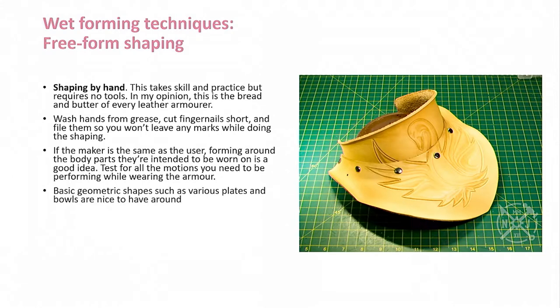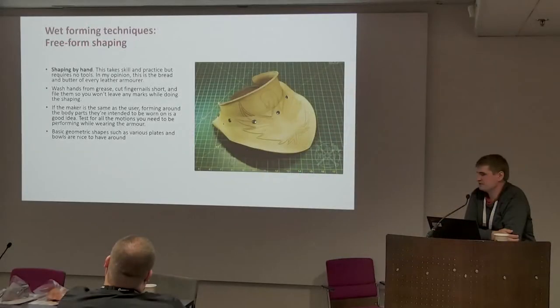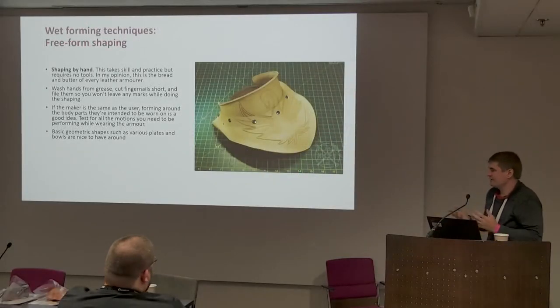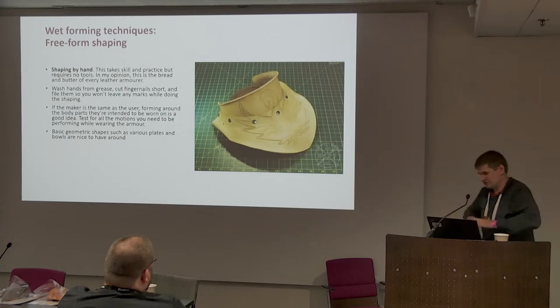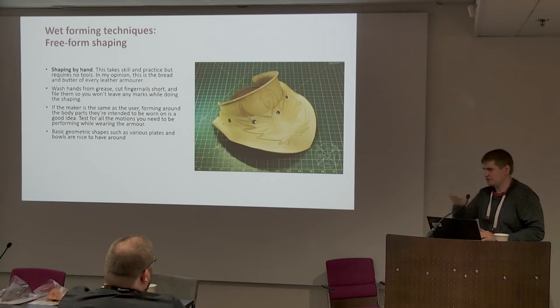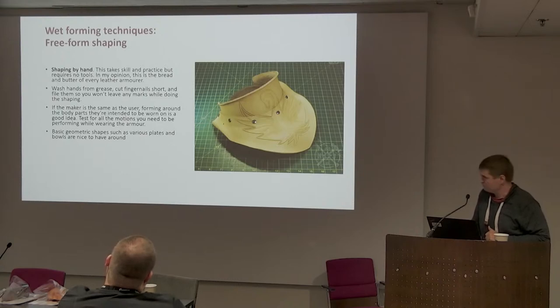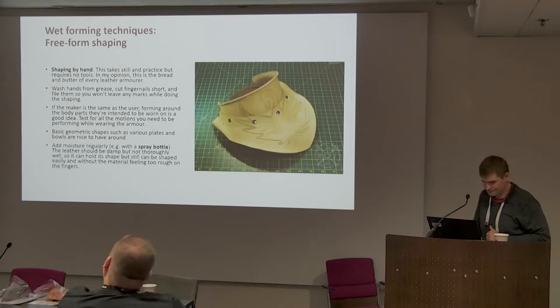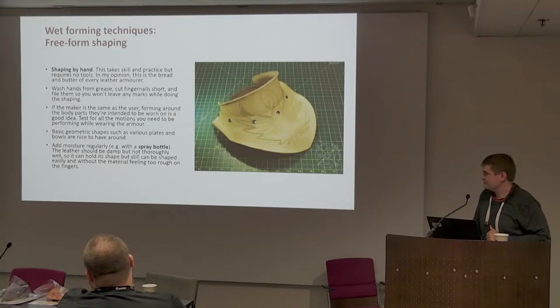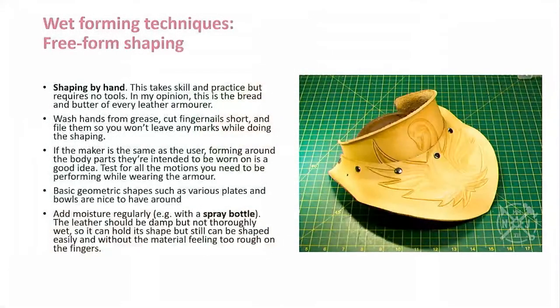A very useful thing with this is to have some basic geometries, like ceramic plates, that you can use to preliminarily shape the leather. So you take a bowl, you shape the leather into a double curvature form, and then you keep shaping it further. It really makes for easier and stronger constructions. Just add moisture regularly, for example with a spray bottle. The leather should be damp but not thoroughly wet, so it can hold its shape when you shape it. If it's too wet, it won't hold its own weight and so forth.